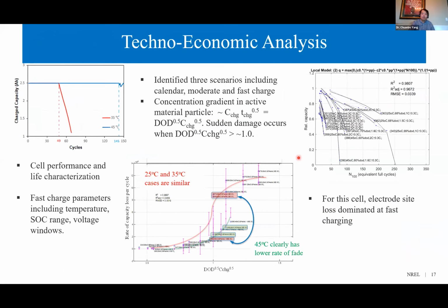To compare the long-term battery use strategies, a battery model analysis is crucial. This was achieved by NREL's lifetime model. This model is a predictive model, extending expensive live battery aging datasets to real-world scenarios. Degradation mechanisms, along with temperature and cycling factors, are regressed to produce a lifetime prognostic model.